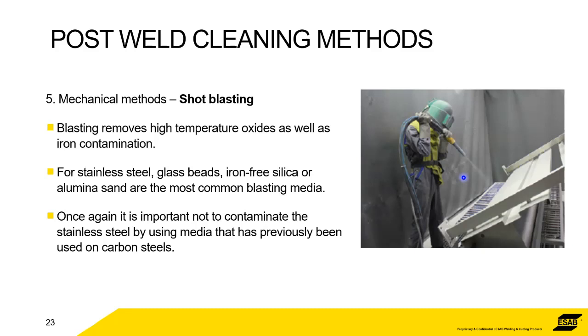Shot blasting is an option, and again, it's not selective. You're just taking off the surface of everything. It will obviously remove oxides and iron contamination, anything that's on the surface. And for stainless steels, the media that people use is glass beads mainly, iron-free silica, alumina sand. Obviously, you don't want steel shot in there for obvious reasons.